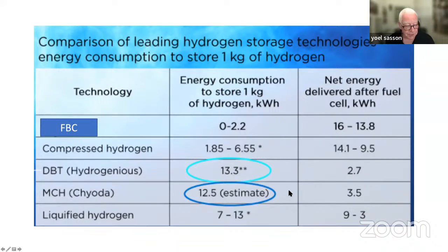So most of it you waste on the process. Chiyoda is left with only 3.5 kilowatt hour per cycle, per 1 kilogram hydrogen, while our process, the formate bicarbonate cycle, will have somewhere between 14 to 16 kilowatt hour left, net energy in the process. This is very, very unique and obviously an advantage over Chiyoda, which is already proven as a commercial technology.